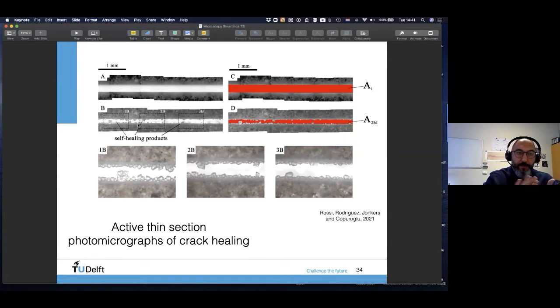So you don't just prepare the thin section, but you also make sure that the cracks are free and accessible, so that from outside you can inject water and try observing crystal deposition, crystal generation in the cracks in this form. So this is a relatively unorthodox technique, so to say, but your keyword to search for is the active thin section.